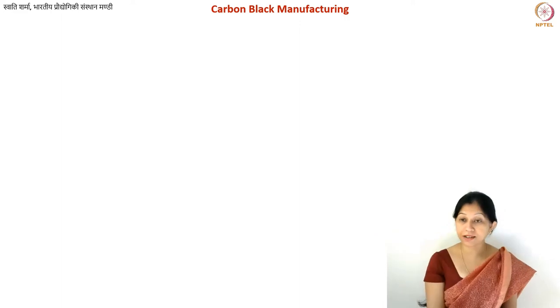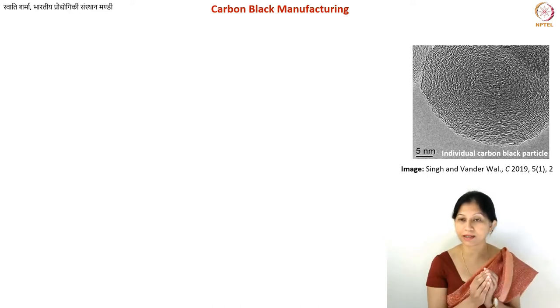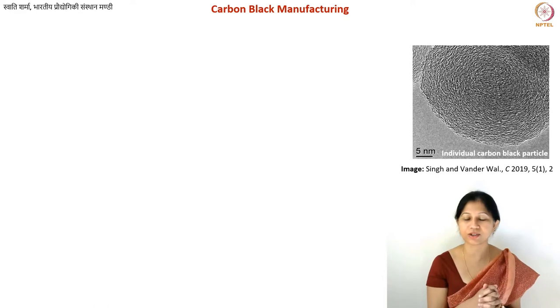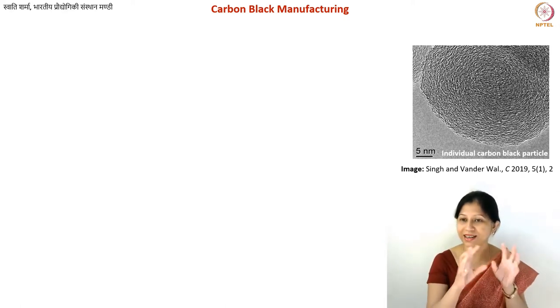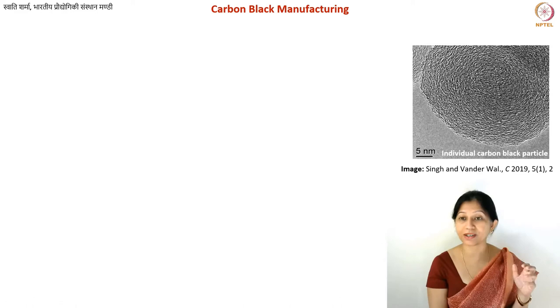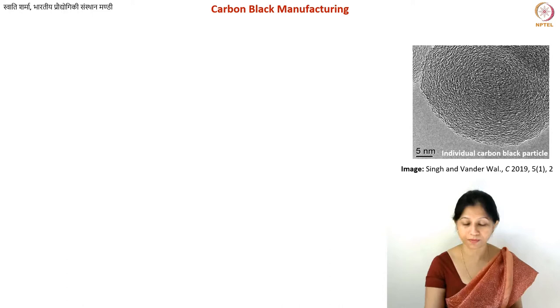Let's talk about the manufacturing of carbon black. Carbon black is nanoscale carbon particles formed by controlled combustion of certain hydrocarbons. These particles are fused together to form larger clusters in the one micrometer size range. You can see in a transmission electron micrograph how these crystallites are organized inside carbon black particles. Carbon blacks also contain some impurities like tars, but the important thing is having these nanoscale particles with a bunch-of-grapes morphology. Carbon black is not soot.